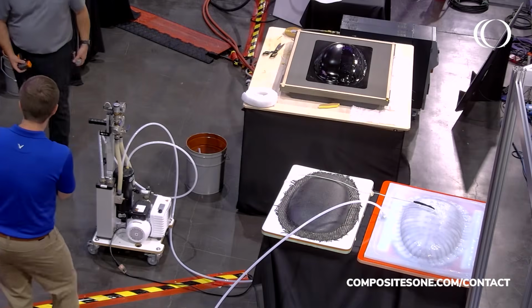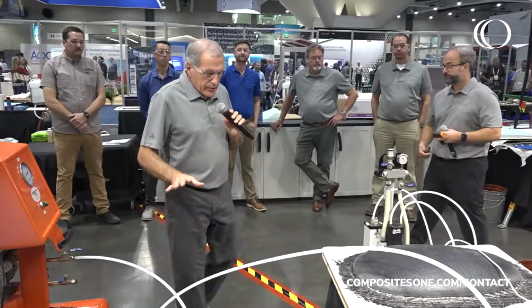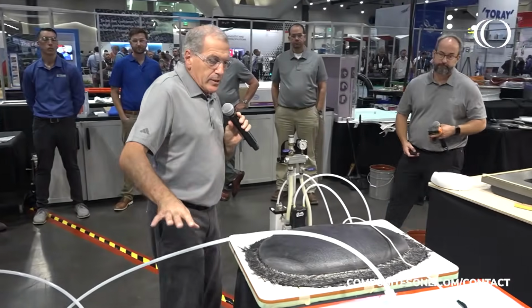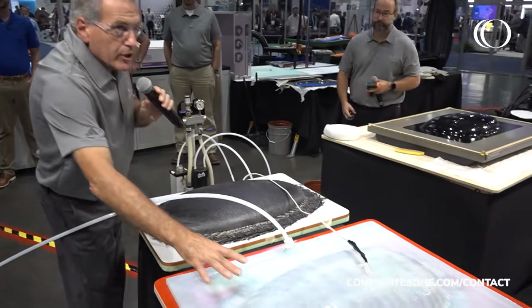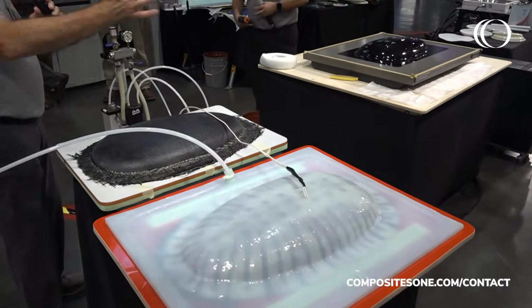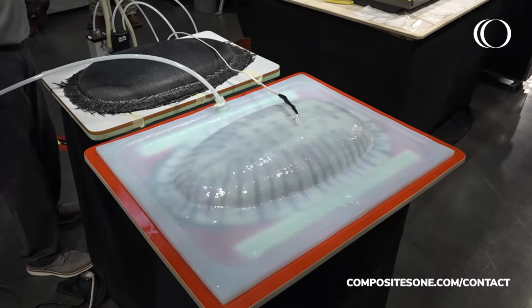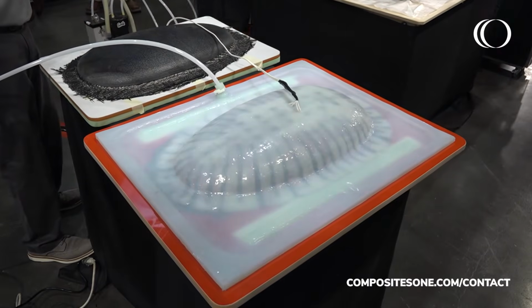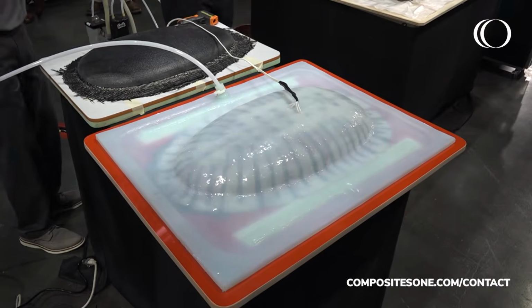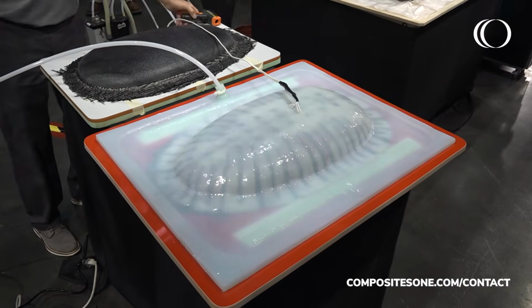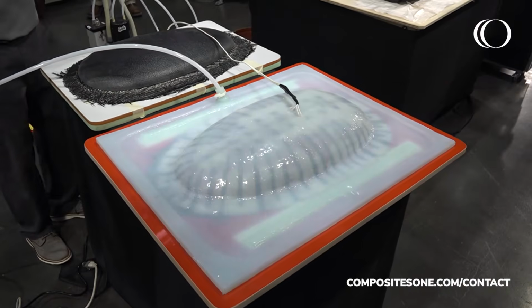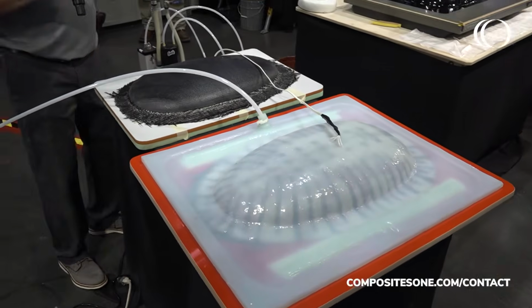Thanks, James. Just going to touch a little bit on this silicone bag that we made. A couple years ago, we did a preform demo, basically with the same material, but we used a bagging film and a heat gun to activate the glue. As Brandon mentioned, the glue needs to activate at about 220 Fahrenheit.